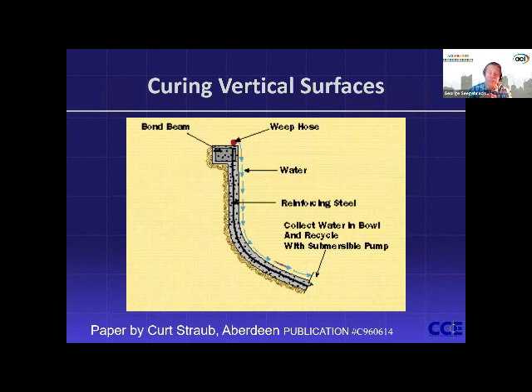Similar, this is from a paper from ASA, American Shotcrete Association, on curing pool walls. Kind of a similar thing where they lay soaker hoses on the top bond beam, which is the beam all the way around the top edge of the pool, and then run the water down with soaker hoses. And then as it comes down to the bottom of the pool or the bowl, they can repump that up and keep recycling that water, which is good. Again, vertical, with shotcrete, you don't have forms, so there's not forms to leave in place, but these guys wrapped in plastic and it worked out well.